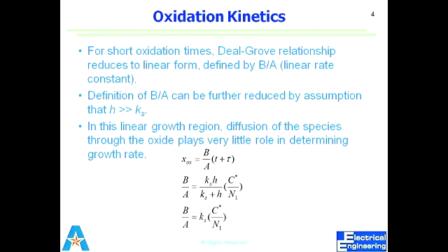Okay, so we have completed the linear region, that is for thin oxide layers. We say this is the linear region because in this region the oxide grows linearly with time, and in this case the limitation is the reaction rate constant.